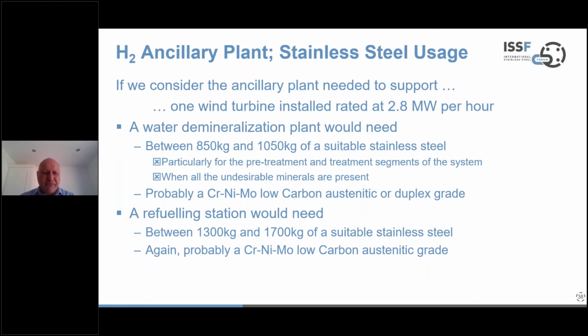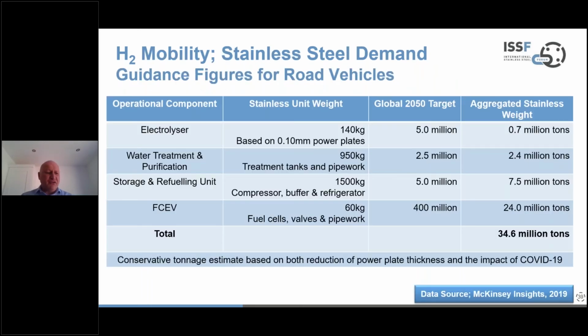As I've said, a low carbon austenitic or duplex grade with molybdenum present would be a good material choice here. When you consider the refueling station, you're looking at more like 1.5 tons of stainless steel, and focus now on an austenitic grade to avoid that ductile to brittle transition that I mentioned. If we wrap all that up, and I've not talked specifically about the vehicles, but it's well understood that fuel cell vehicles need about 60 kilograms of stainless steel, not just in the fuel cells, but associated valves and pipework for the hydrogen delivery system.